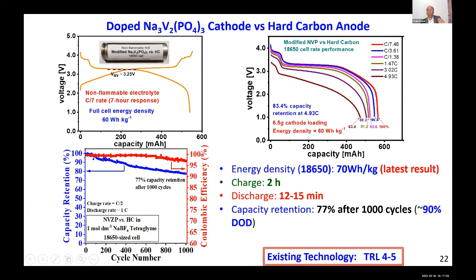Here I'm showing you the rate performance. Typically, the charging rate is somewhere about C/2, 2 hours, but discharging, I can go by 7 hours, or I can go by about 5C, closer to 5C, 12 minutes. So if I discharge in 12 minutes, I'm still able to retain 83% capacity. That's very important. This is yet another impressive data. 1,000 cycles we are able to do with a 90% DOD, depth of discharge, and retaining about 77% capacity.